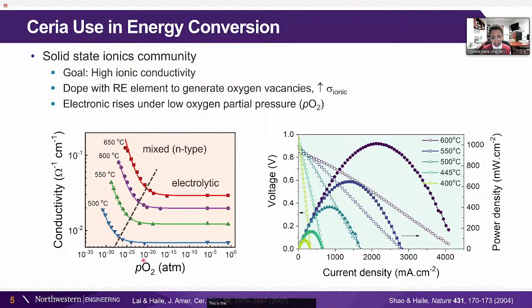This is the conductivity of the material as a function of oxygen partial pressure and various temperatures. We have an electrolytic regime when it is under reducing conditions, meaning a low oxygen partial pressure. The conductivity rises because it starts to go a little bit n-type, because you start getting some of the 4+ cerium becoming 3+, which gives very high conductivity.